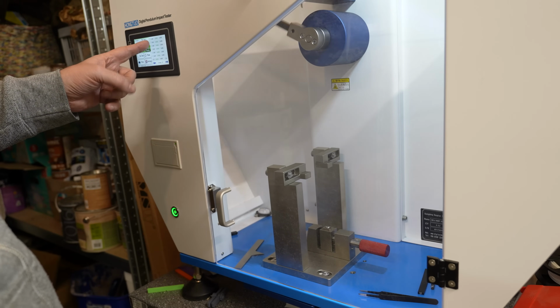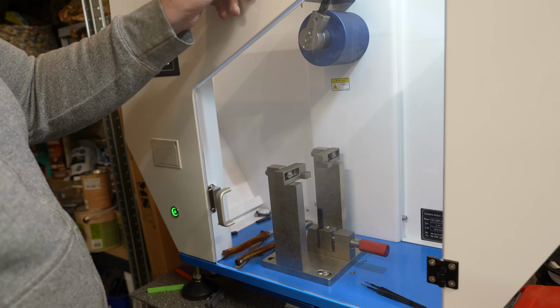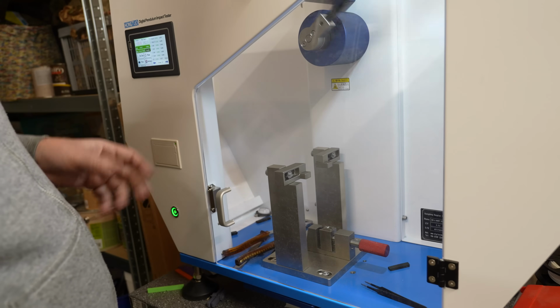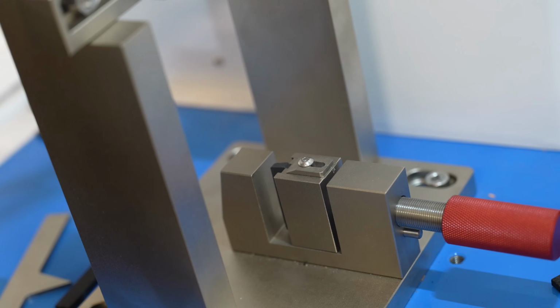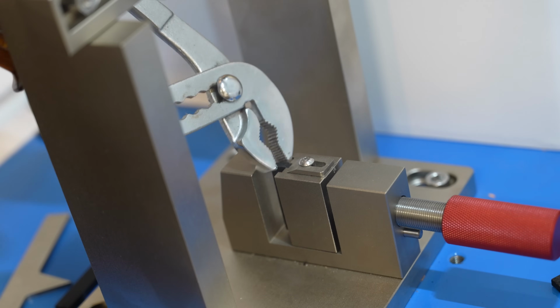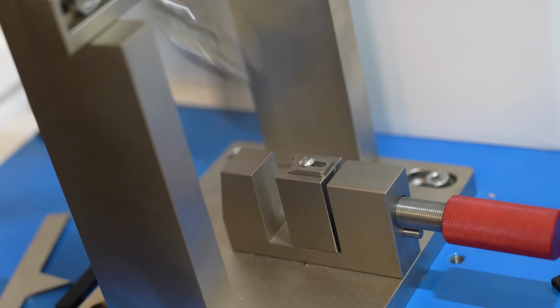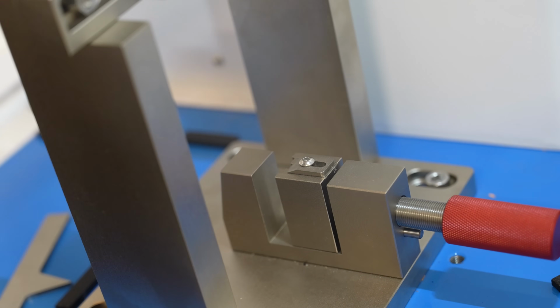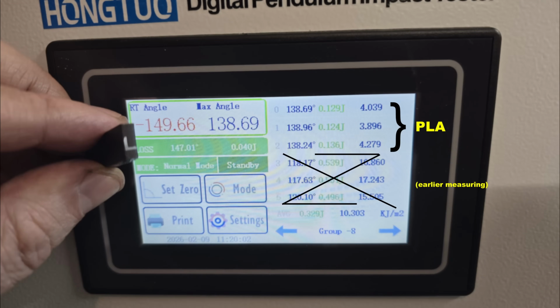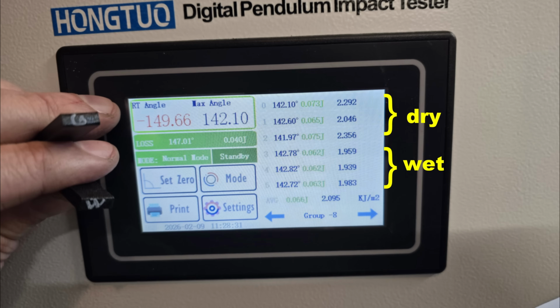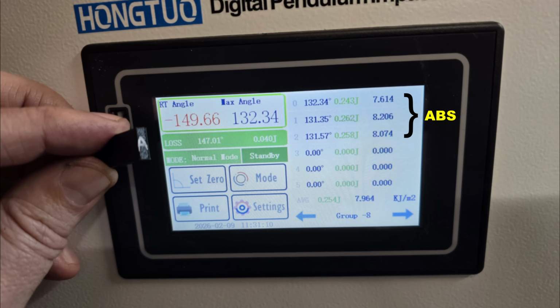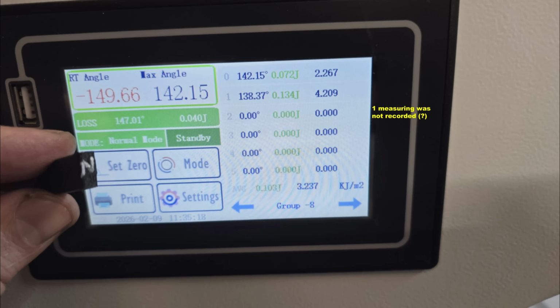Wow, so weak that it's not even measurable. Nylon again. It is still so wet that it is over extruded and too big for this holder normally, and it's stuck inside. Okay. Not really measurable data, and the first one break even without number. PLA, PETG dry and wet, ABS and nylon.